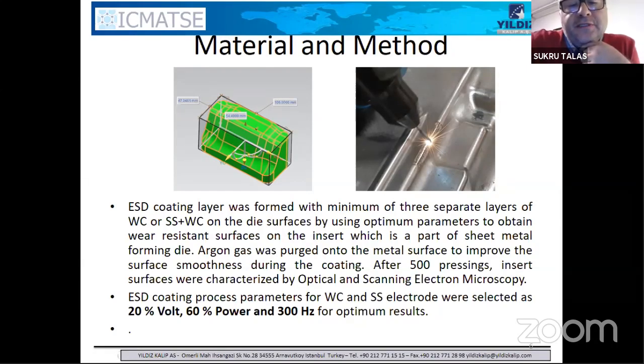So we use 60% power and 300 hertz. 60% power is approximately 25, 26 amps, and it would be enough for us because we don't want to create a very hot surface. Another advantage of this process is that when you're welding the surface, the heat generated is not high enough to create a metallurgically different substrate, and it doesn't affect the metallurgy or microstructure of the substrate. So it's very important. So we coated the surface, as you can see in the picture.